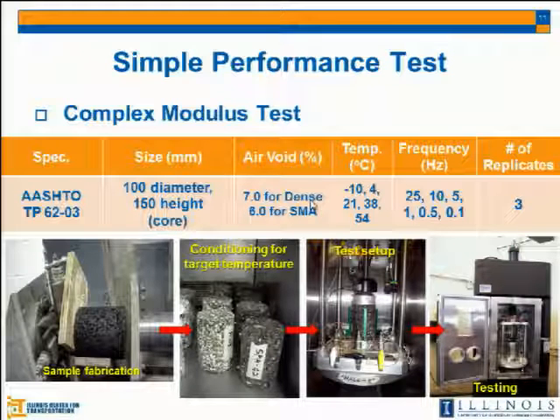If you see here the air void for dense grade mix and SMA mixture, actually we tried to have the same air void, but from the discussion in the TRP meeting, for dense grade mixture we are targeting 93% of the density in the field, but for SMA mixture we are targeting 94% of the density. So if we compact this SMA mixture to have the 7% air void, it's not correct in the field. So that's why we decided to have the 6% air void for all of the SMA mixture.